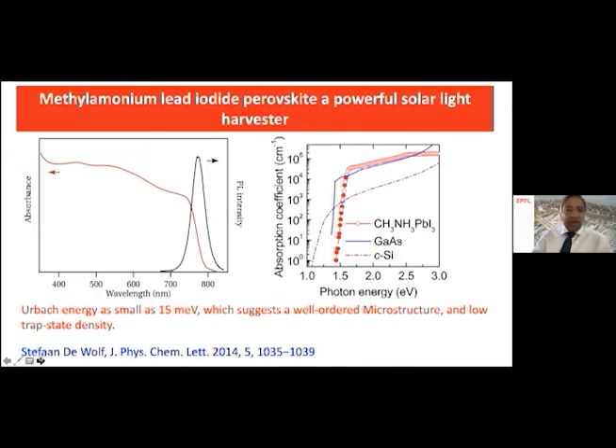Now, as I mentioned, the absorption spectral properties are shown on the left side. This is the absorption spectrum of a typical perovskite absorber. When you excite at this absorption maximum, you can see a typical emission maximum coming around 780 nanometers. Another important property of this perovskite, which I have not highlighted in the previous slide, is the sharp onset. Look at the onset of gallium arsenide, the champion cell having 29% efficiency. And look at crystalline silicon solar cell, the onset is sluggish. And the perovskites have a sharp onset similar to gallium arsenide.